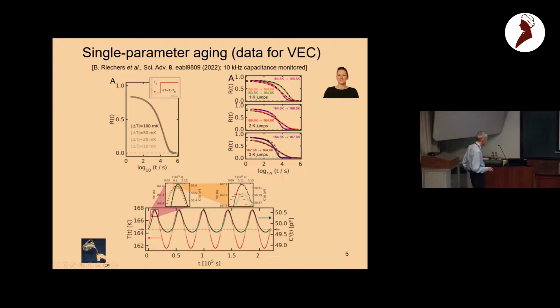So we wanted to go one step further, because once you have the linear response theory you can do any temperature perturbation. It doesn't have to be a jump. So we wanted to make a sinusoidal one. The red curve is the temperature variation here, 3 Kelvin sinusoidal, with a roughly 12 hours period. The black curve is the predicted one from the linear experiments, and the turquoise is the measured one, which fits nicely. And again, there are no fitting parameters in this prediction.